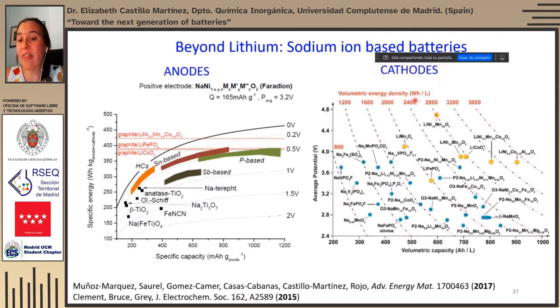On the other hand, if we look at the cathodes, we can see here in yellow the volumetric energy density and capacity of lithium layer oxides, as well as many different sodium cathode materials. We can see that for layer oxides, we have many more compositions than for lithium ion, and this is due to the fact that you can de-intercalate sodium ions from layer oxides of many more transition metals, not only cobalt and nickel. Also, polyanionic compounds, phosphates and fluorophosphates have been tested, as well as some hexacyanometallate or Prussian blue-based materials, which on the other hand have lower volumetric energy densities, therefore do not appear in this plot.